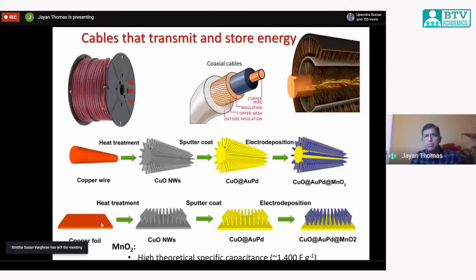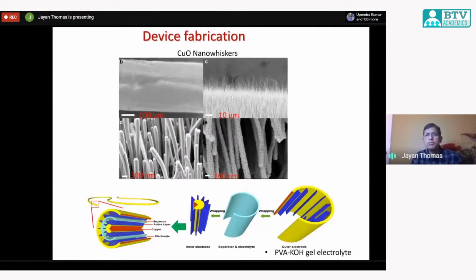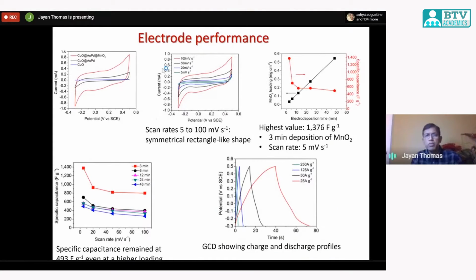Here you can see some SEM images of the nanowires. It's a beautiful structure, with nanowires about 200 nanometer diameter and 20 to 22 microns height. So you can see that the aspect ratio is very high in these cases. This can be done very easily, and this is the process we use. This is the internal cable, the separator, and the outside covering. That's the first report, which was published in Advanced Materials, and here is the electrode performance, which shows that it's a reasonably good storage device.